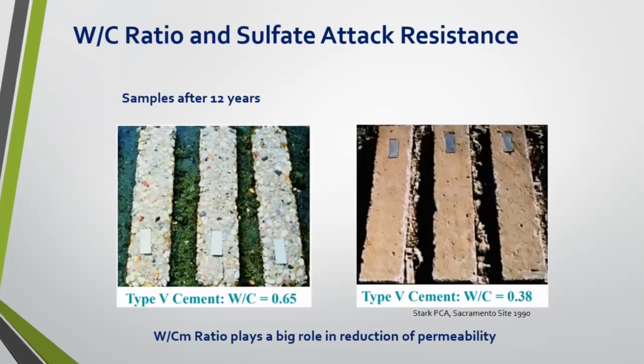So we talked about water cement ratio already, and the benefits of that and sulfate attack resistance. The pictures here that you're looking at were both produced, these beams were both produced with concrete that had a type 5 cement. The difference being that the one on the left has a water cement ratio of 0.65, on the right, 0.38. And these samples that we're looking at are after 12 years being exposed to a sodium sulfate solution. I don't know anywhere or anyone that would look to put a 0.65 water cement ratio in structural concrete. It'd be a rarity, but this does a good job of showing you the disparity between those two and what the effect of water cement ratio is on that reduction of permeability, and permeability's role, conversely, in mitigating sulfate attack.